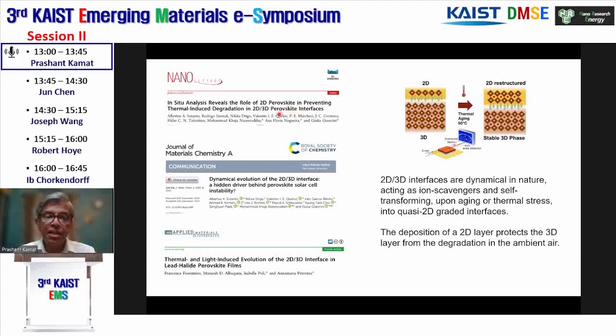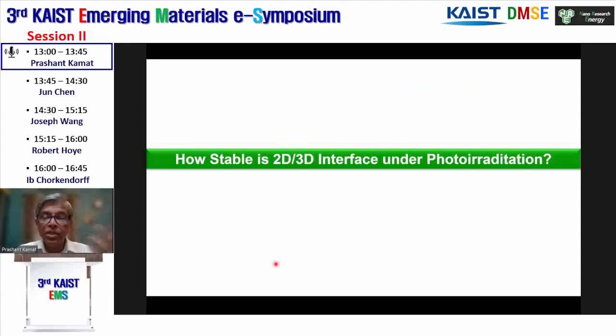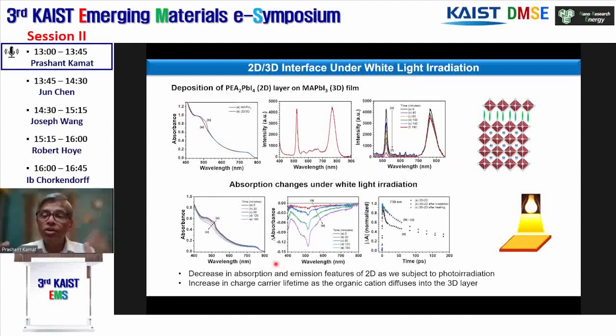For example, in the literature, there are several papers showing that the spacer cations are dynamic. They diffuse into the 3D, and most of the time it is thermal. Various people have used strategies to detect this kind of movement of ions. So now the question is, how stable is the 2D-3D interface under photo irradiation? It's a very simple question and a very simple experiment. What we did was we took a 3D layer, exchanged the spacer cation, and created a small 2D layer on top of it. Again, we followed the same recipe people use for making solar cell performance better.